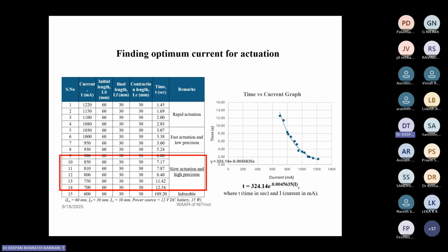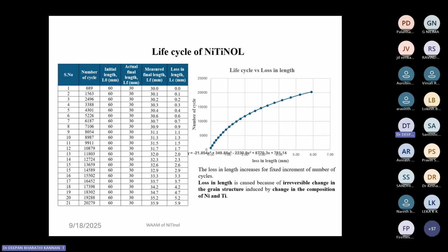So in our future project, we can try to play with the amount of heat that we are giving, and accordingly we can control our actuation. They also studied the life cycle of this fabricated spring, and they found that after 20,000 cycles, the loss in length is only around 5.9 mm. We could also explore this by altering the chemical composition and studying the current that we are applying. For 689, the loss in length is 0, so we are able to recover the complete shape. And for up to 10,000 cycles, the loss in length was only around 1.7 mm. And after 10,000, it increased to 5.9.